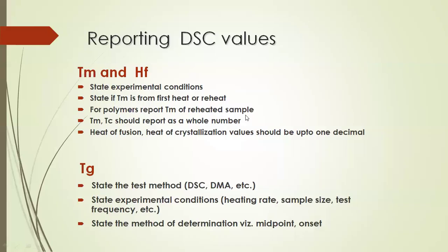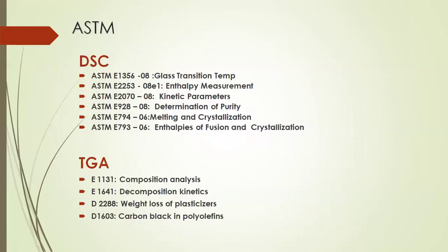For polymers, always report the melting point of the reheated sample, because a polymer remembers its history. So the first heating melting of a polymer always has the processing history. So for polymers, you have to report the second heat melting. Heat of fusion and heat of crystallization values should always be up to 1 decimal, not 2 decimals. For Tg, the glass transition temperature, state the test method by which you have reported it, state the experimental condition, and always state which point you have taken, onset or midpoint. Because many people report Tg as the midpoint of a step change, many people report it as the onset of the step change. So you always report what your style of it is.